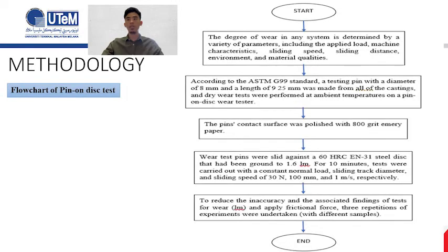And then the pin contact surface was polished with 800 grit emery paper. And then the wear test pins were weighed again. So the last one is, to reduce inaccuracy in the associated findings of the test for wear and applied frictional force, 3 repetitions of experiments were undertaken with different samples.